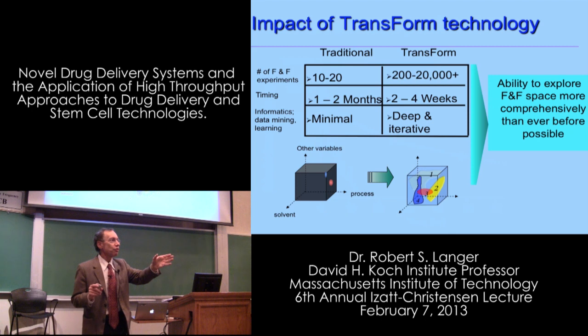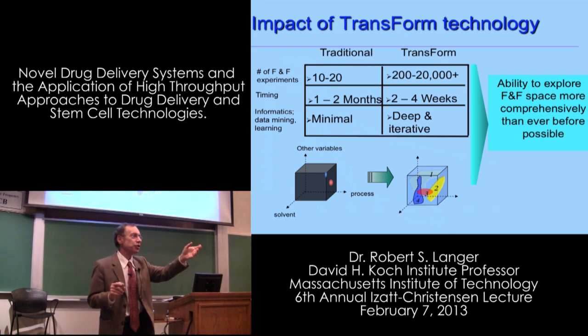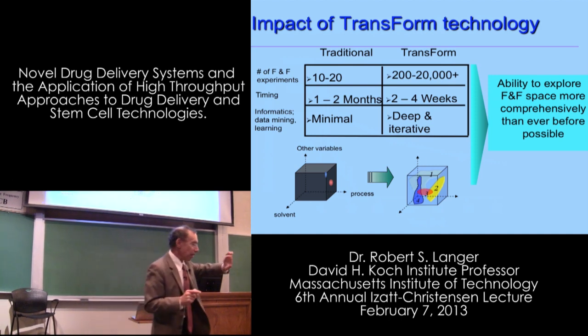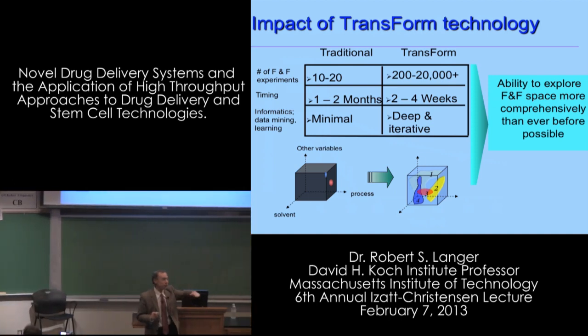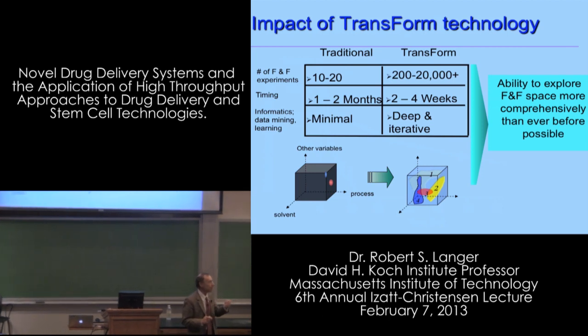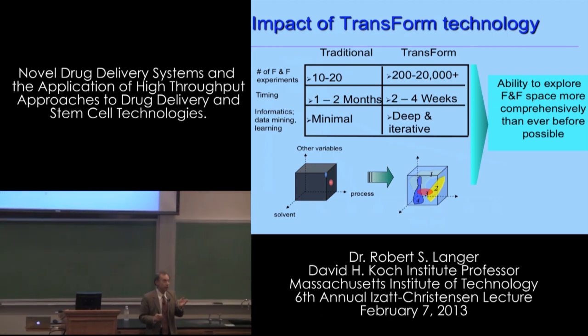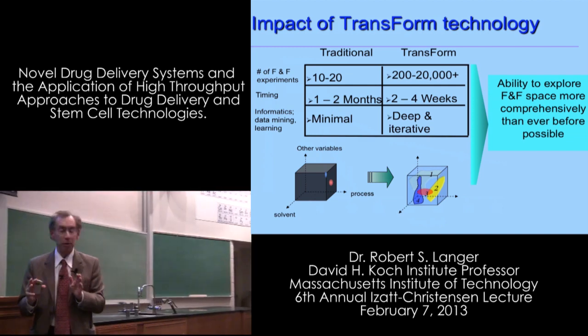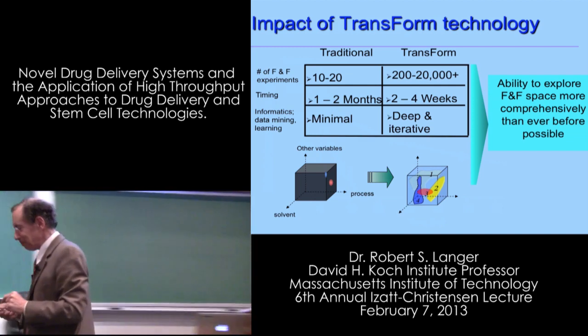We have little robots where the first thing is crystallization to make polymorphs. So rather than do them by hand, we have little hotel rooms almost. There's going to be different seeding conditions, which could be different temperatures, different surfaces, and so forth. And we're going to see what kind of crystals we get. We're going to analyze them several ways: melting temperature, Raman spectroscopy, X-ray diffraction, so three different methods. I'm going to show you that, and then at the end a set of experiments on solubility. But if we could just go to the video.